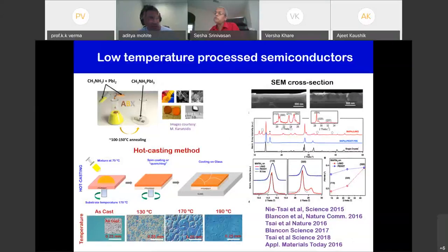And so this was really our first entry into the field of perovskites. This field was rejuvenated in 2011 when Henry Snaith came up with his seminal papers showing 12% efficiencies with these cells. And so we really got into this game only 2 years late. The way we started, we were trying to make some thin films made out of perovskite. And we developed a new method, which we call the hot casting method. The idea here is that you have a substrate that is hot, okay? And you take a precursor mixture with the right molar stoichiometries, put it down here and start spin coating the substrate. As the substrate is spinning, it's also cooling down. So the substrate is hot. That's why the name hot casting.